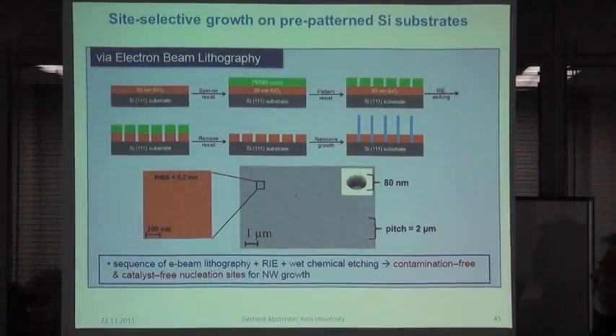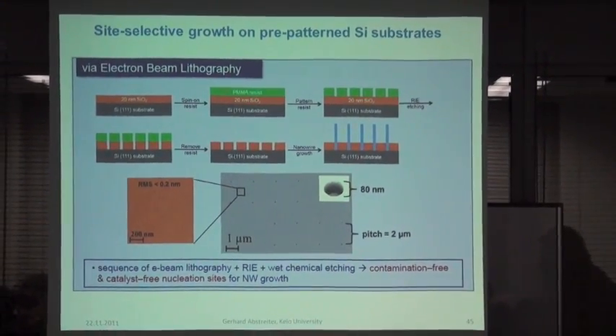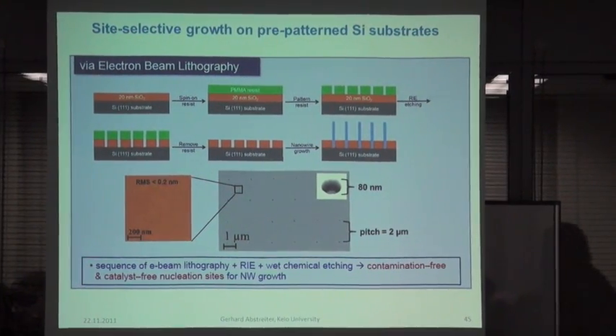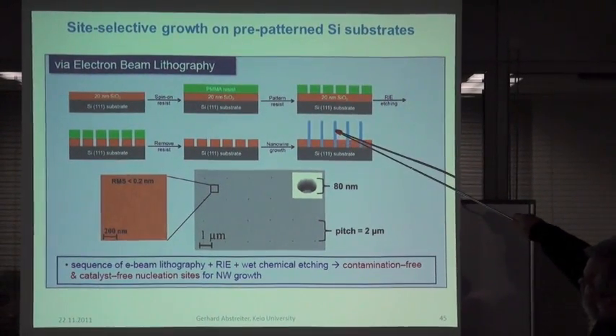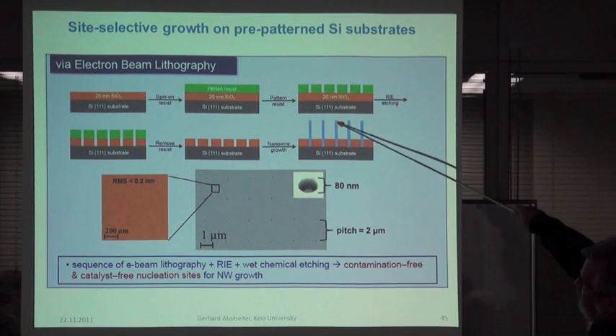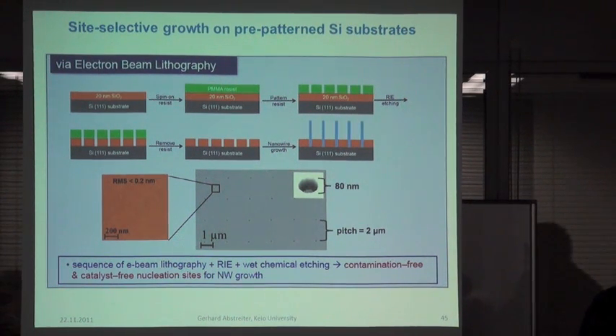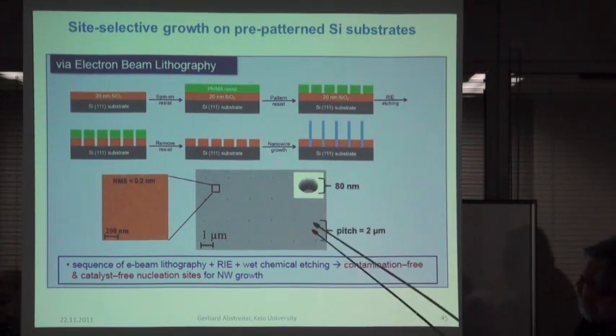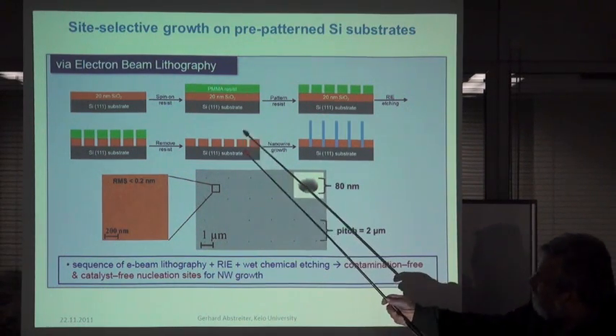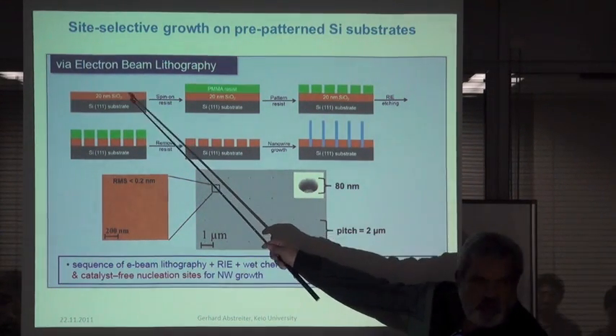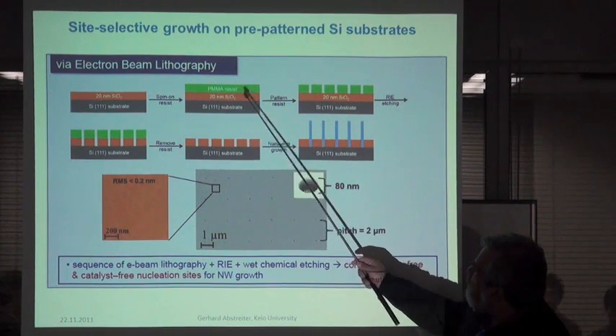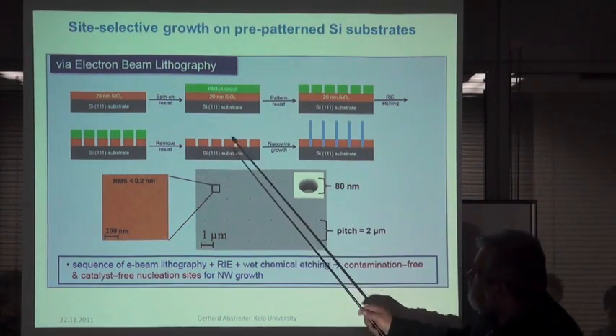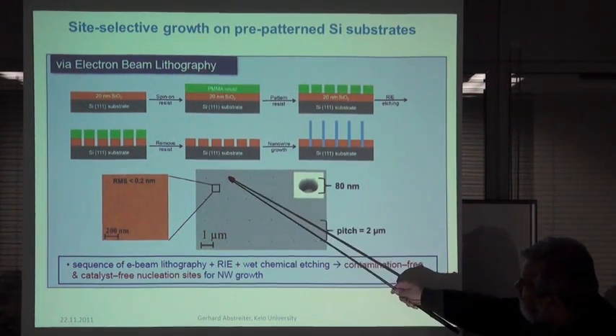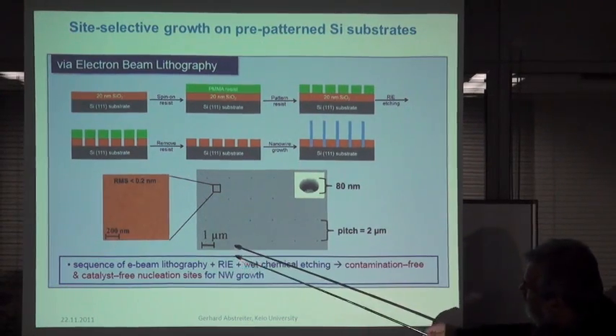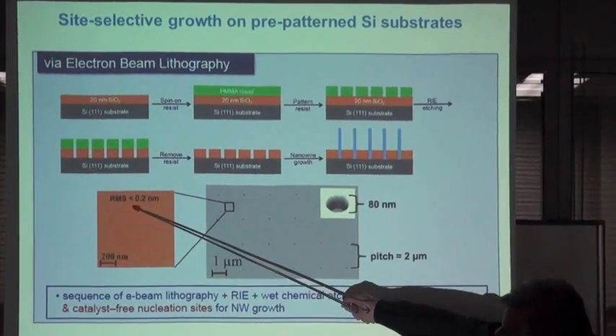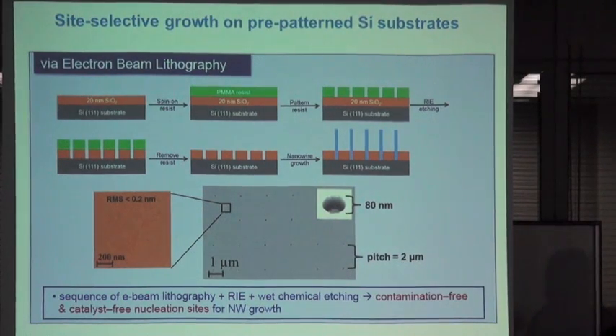Now, the question is, can we do this also in patterns? This is important for maybe applications in future. And we bring also in the moment, let's say, quantum dots inside these nanowires by changing the composition. Now, we just used a silicon substrate with 20 nanometer oxide. It's a thermal oxide. And then we pattern it, and we have then these holes, at regular distance. So the flatness is very good. It's 0.2 nanometers of this oxide.